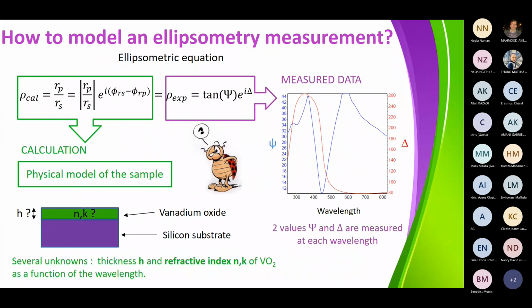Okay, to analyze this data, here you can see the measured data with the psi and delta, the ellipsometric angles. And from these ellipsometric angles, you can calculate, thanks to the ellipsometric equation, the experimental ρ, which is equal to tangent psi exponential i delta. This is an experimental term, but this experimental term is also equal to the theoretical term, which is the ratio of Rp to Rs, where Rp is the Fresnel equation for the reflection when the field is parallel to the plane of incidence. And Rs is the one where the electric field is perpendicular to the plane of incidence.